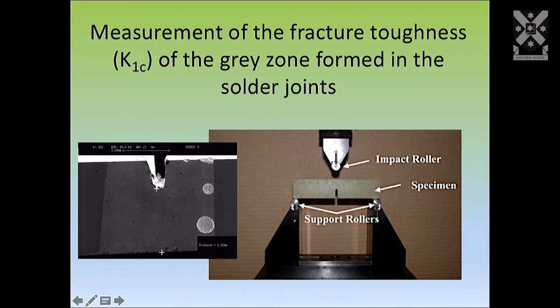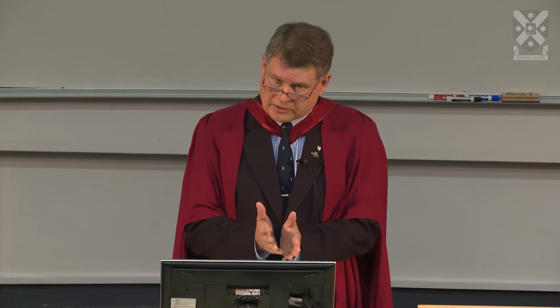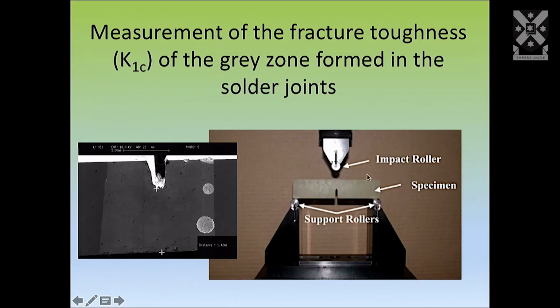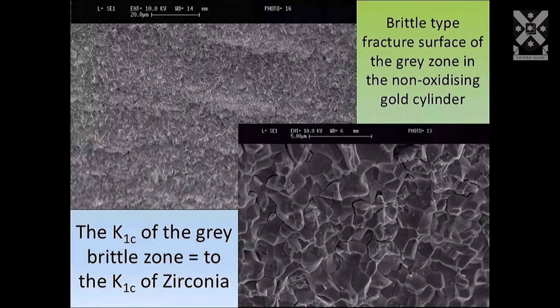So we made up beams, and in the beam we incorporate some of the non-oxidizing gold cylinder on one side and the solder on the other, and this is what we call a fracture toughness test. So we notch it here to induce the crack to the direction and the area we want the crack to occur in. We load it in a 3-point bend, and then once we break it, we are able to calculate the fracture toughness.